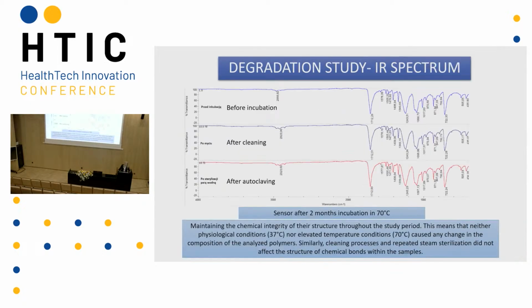And also here we can see the sensors' IR spectrum after 2 months incubation at 70 degrees, and also after cleaning and autoclaving. Here we can observe that we can maintain the chemical integrity of the structure for the study period. Also, cleaning processes and repeated steam sterilization did not affect the structure of chemical bonds within the samples.